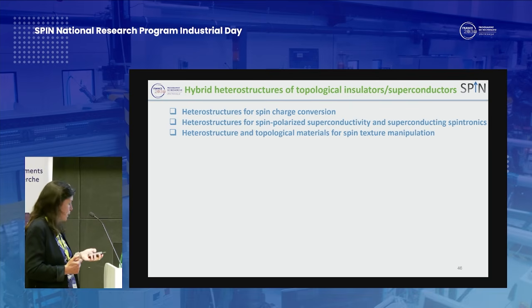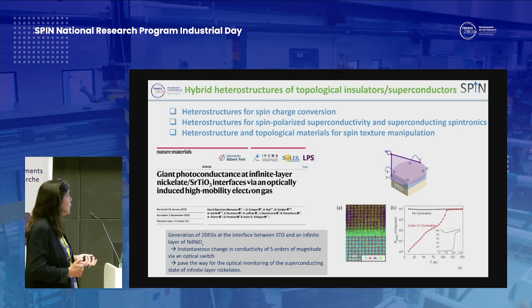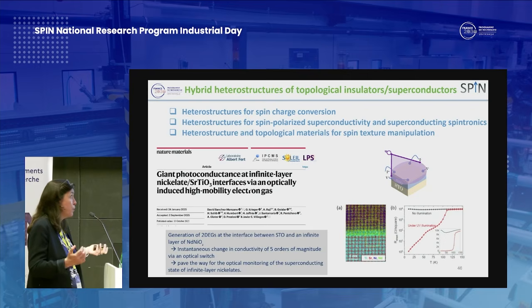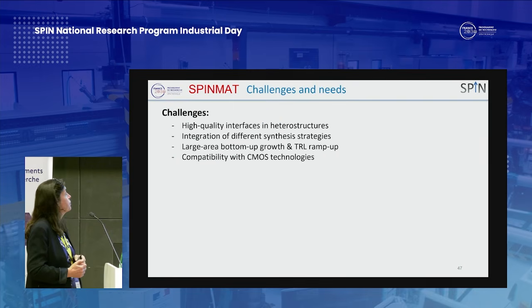for spin texture manipulation. As an example, here's a generation of a 2D electron gas at the interface between STO and a layer of nickelate. And the conductivity can be tuned by 5 orders of magnitude via an optical stimulus, which opens the way for optical monitoring of the superconducting nickelate. So from all these examples, you see that there are a lot of challenges that need to be addressed.